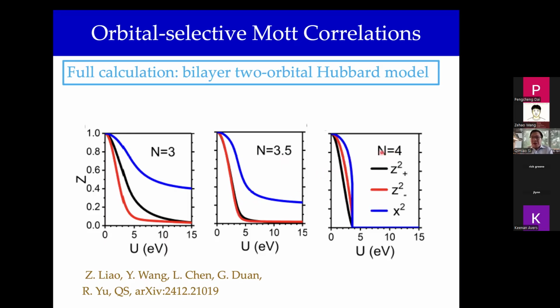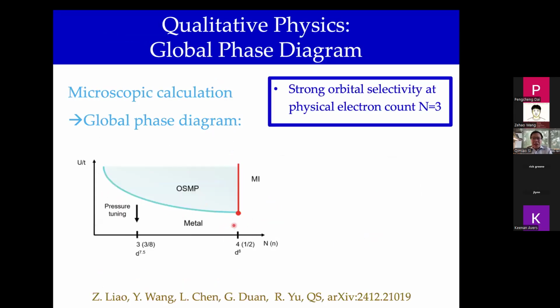And we can march further to n equals 4 electrons in these four 3d orbitals. And so there's still the differentiation of the renormalization factors among different orbitals, but the system being at half filling can get into the Mott insulating phase in a much more ready fashion compared to the other fillings. So if we put all these together qualitatively, n equals 4 is the half filled case where we have the metal and the Mott insulator, and n equals 3.5 is here, n equals 3. The physical case is here, and ambient pressure, ambient condition to applied pressure case would represent a tuning like this.